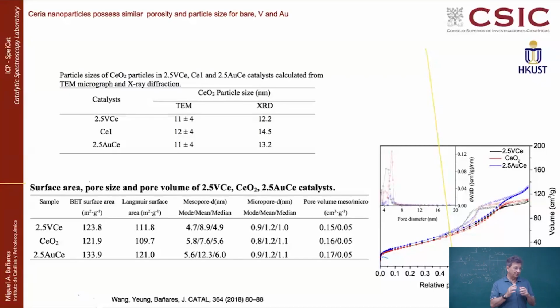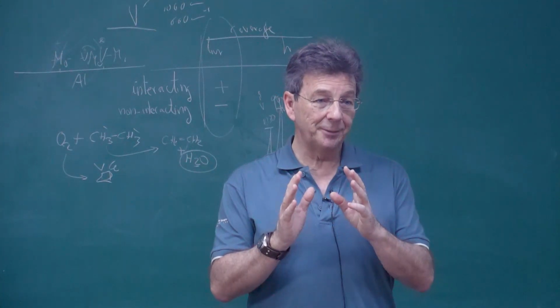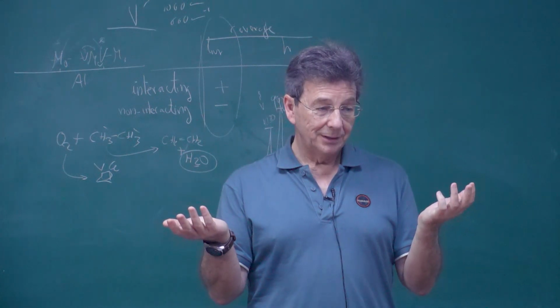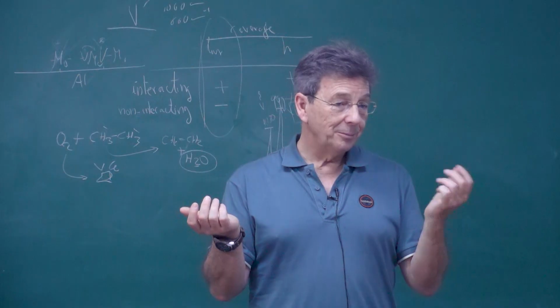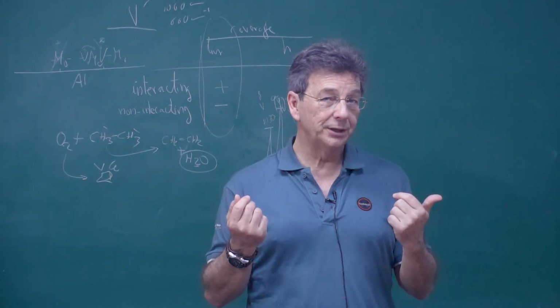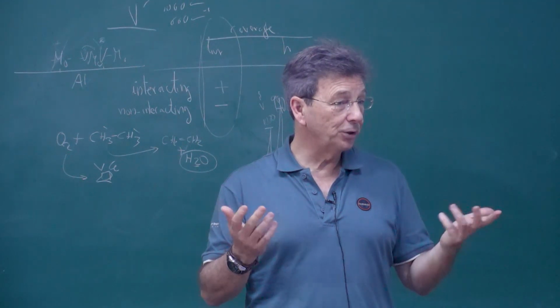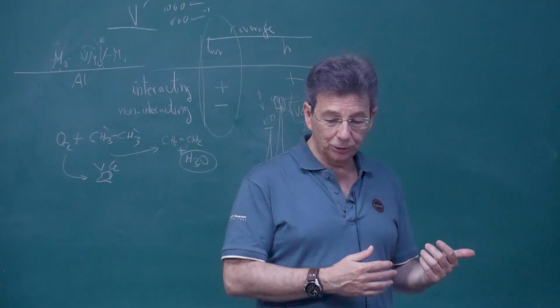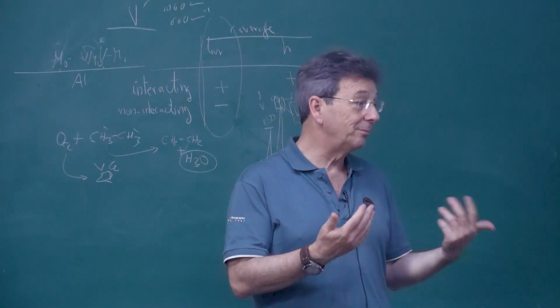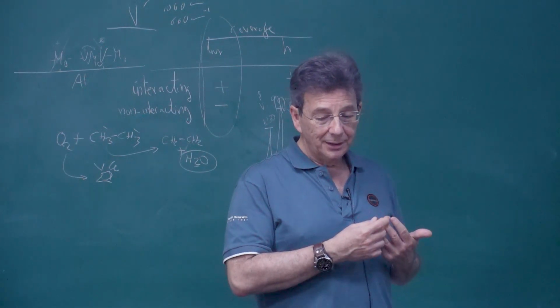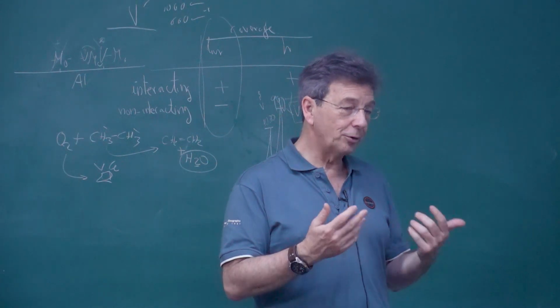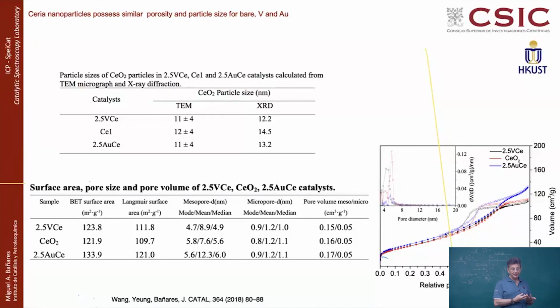Why do I want to do that? Okay, because ceria has a big oxidation capacity. With gold, it will be an excellent combustion catalyst, and there is an application for that. With vanadium, it is a partial oxidation catalyst. So somehow it's like two additives that will make ceria selective oxidation and total oxidation. Selective oxidation was interesting if you want to make ethylene, but total oxidation is interesting if you want to work in combustion, for instance, of volatile organic components for indoor air quality. The same way that the other day we were telling about inactivating airborne pathogens, virus and bacteria by oxidative damage, killing virus and bacteria, we also want to decompose molecules, toluene, formaldehyde, many other chemicals which are in the air and that have to be removed. And for that reason, we were looking at these two systems.